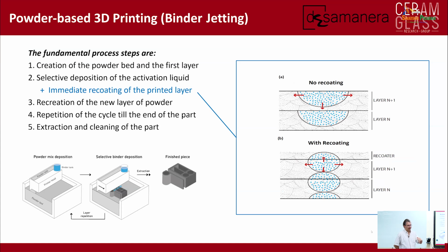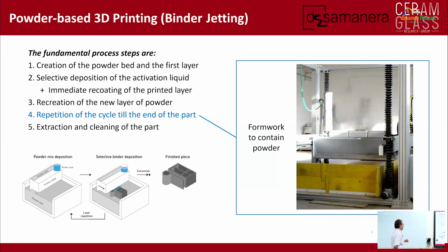We spray just after depositing, and then the rest of the thickness of the layer is deposited on top of the sprayed region. And we found that this is the best way of obtaining a layer which is a thickness of a few millimeters where the liquid is homogeneously distributed.